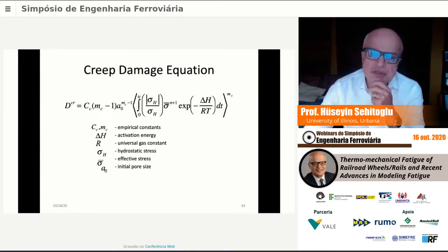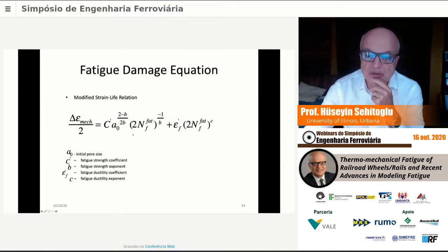The creep damage is the integration of the hydrostatic stress, which would be the mean stress in the cycle, and the effect of mean stress as well as the Mises stress. This is the effective stress in the cycle. Again, there's an exponent here, like a creep exponent, and that's the activation energy. So that's the integration of this damage term within the cycle, and that gives us an evolution of the creep damage.